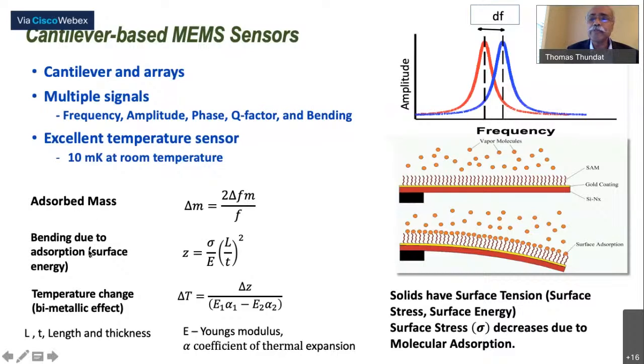The bending: suppose you have a cantilever, a little like a miniature diving board. Most of the sizes of these cantilevers are around, say, 100 microns. That's what we prefer, 100 to 200 microns, and 1 micron in thickness. And if we have asymmetric adsorption of molecules, the surface tension of the surface, like silicon, will change. Solids have surface tension. We call it surface energy or surface stress.